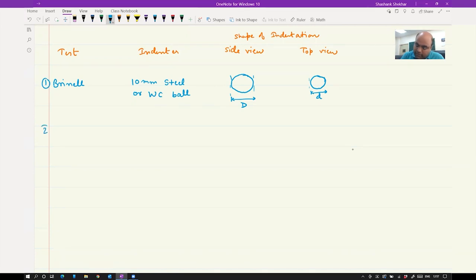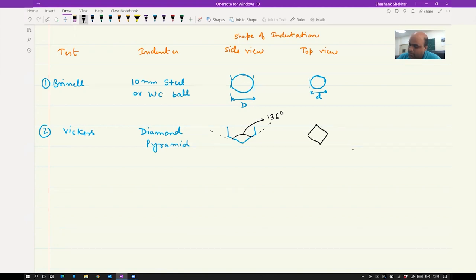So this is one. Second is your Vickers. Here we are using a diamond pyramid. And that was a 136 degree angle, if you remember. So this particular angle here is 136 degrees. This is your side view. The angle between the two opposite faces is going to be 136 degrees. And if you see the top view, it is going to be a square. Then you have to measure D1 and D2. So d is going to be (D1 plus D2) by 2.